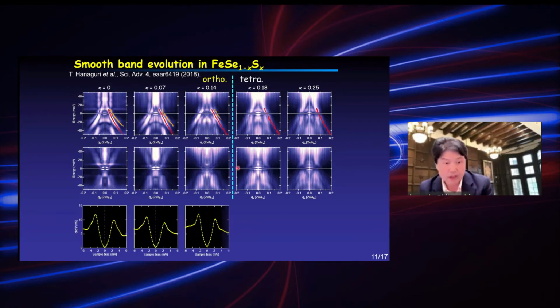However, if you look at the dI/dV at low energies, within the orthorhombic or nematic phase, the dI/dV curves show a pretty similar structure with the V-shaped conductance at low energies. This again shows that the superconducting gap is pretty anisotropic.